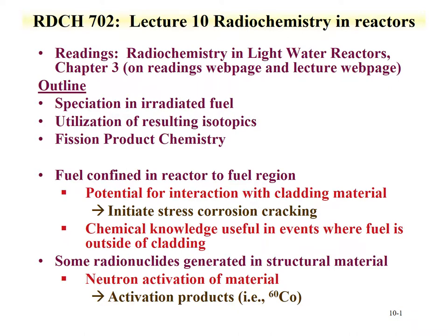In a reactor under normal conditions, fuel is in a confined region surrounded by cladding material in a typical light water reactor. There is some potential for chemical interactions between the fuel and the cladding material — particularly certain lanthanide-type materials, depending upon your cladding material, will have interactions with the cladding. This can lead to poor mechanical properties such as stress corrosion cracking, generally called fuel-chemical cladding interactions. This is an area of study to understand how fission products and their concentrations, hence burn-up, influence cladding material.